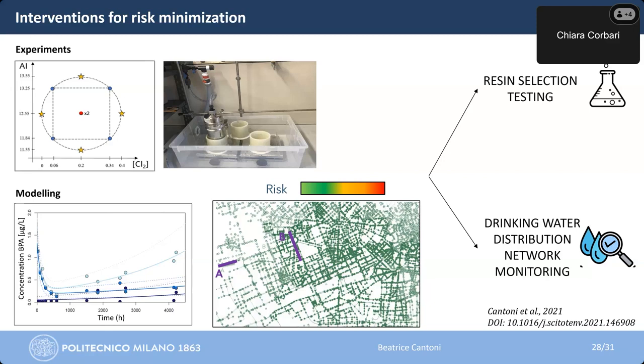These are, again, the dots are experiments, and then we fit the model. And with this kinetic model, we applied it to a hydraulic model to evaluate, in a real case where two epoxy resins are already installed, whether the risk would be exceeded or not. And so green, we are okay, yellow, no, red, not at all. So just to give you an idea.